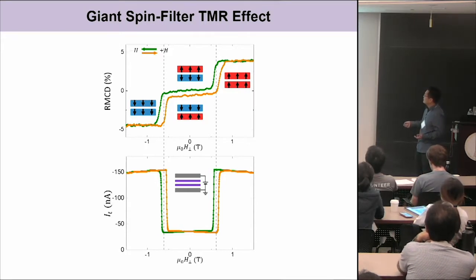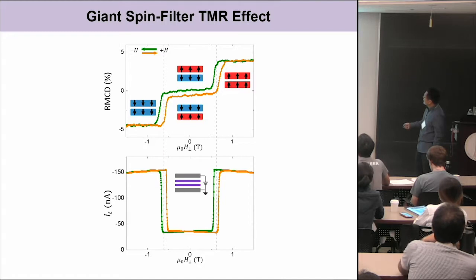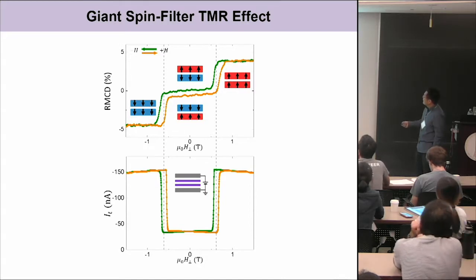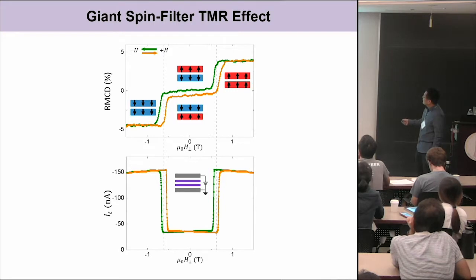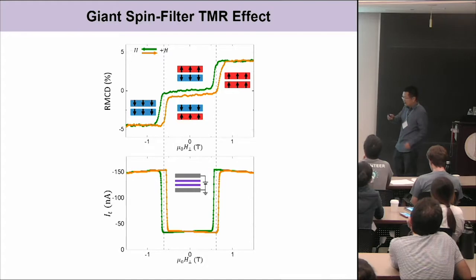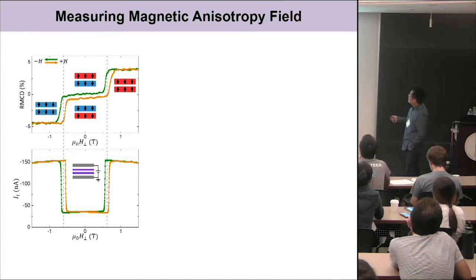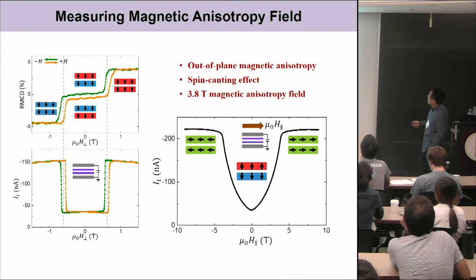We do tunneling measurements. You can see that at low field the tunneling current is suppressed, corresponding to these antiferromagnetic ground states. And when the magnetic field is large, all the spins are aligned and the tunneling current becomes large. So these sharp transitions are spin flip transitions, as we see in these MOKE measurements. Everything is consistent. And we can extend this idea into more complicated systems.